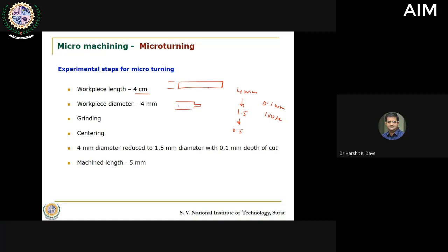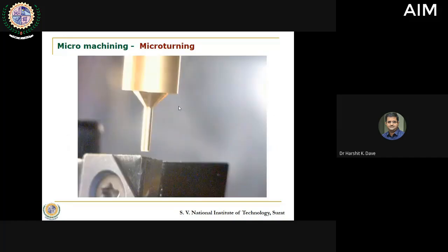Initially we tried to reach 1.5 mm, and all those tools where 1.5 mm was achieved, we further used as a raw material for generating a 0.5 mm diameter shaft. So first we tried to create a basic raw workpiece material with 1.5 mm diameter, on which we worked to go down to 0.5 mm diameter. This is a clip of that activity.